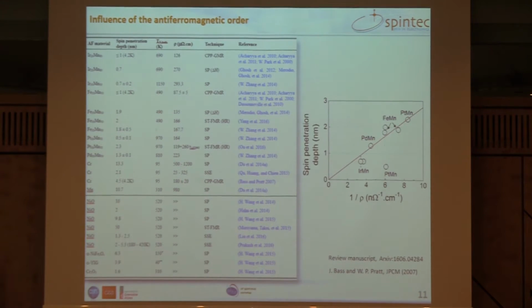So this surely underlines the importance of diffusive mechanisms in the determination of the spin penetration depths. There is a review about spin penetration depths, not in antiferromagnets, but in all kinds of different materials, that clearly explains the evolution of typical penetration depths with 1 over the resistivity.